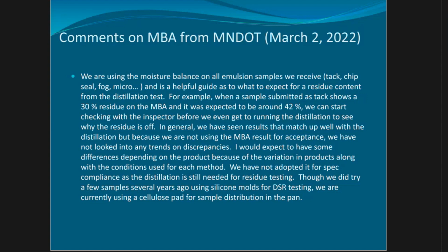We can start checking with the inspector before we even get to running the distillation to see why the residue is off. In general, we have seen results that match up well with the distillation, but because we're not using the moisture balance result for acceptance, we have not looked into the trends or discrepancies. I would expect some differences depending on the product, because of the variation in product along with the conditions used for this method. We have not adopted it for spec compliance as the distillation is still needed for residue testing.